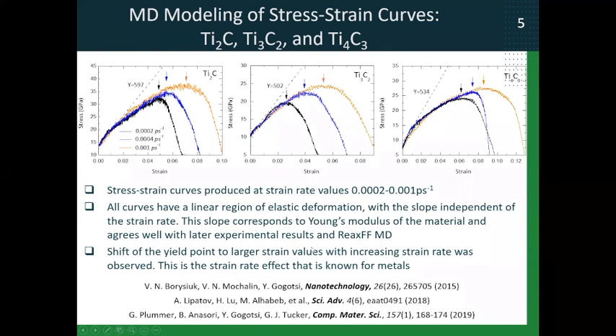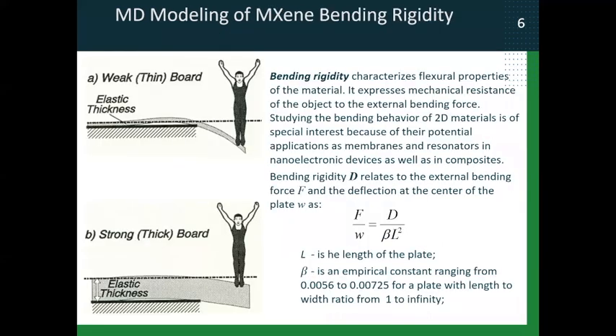And this is consistent with basically metallic nature of MXenes, because they also offer very high conductivity, and electron density at Fermi level is very high. So this is another illustration that they behave basically as metals when you deform them, especially at low strain rates. So you can get information about Young's modulus, about failure mechanisms, and the values of Young's modulus that I showed in previous slide were later on also confirmed by ReaxFF modeling that Yuri presented last time, and also by experiments also done by his group in collaboration with a group at the University of Nebraska-Lincoln.